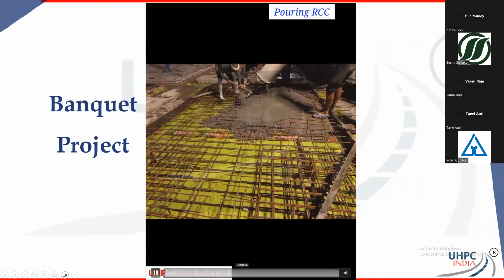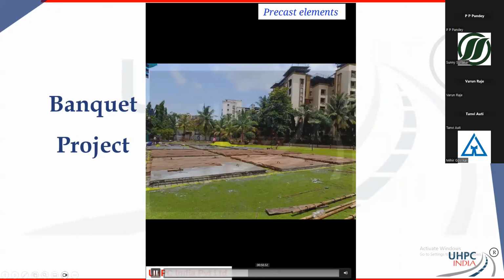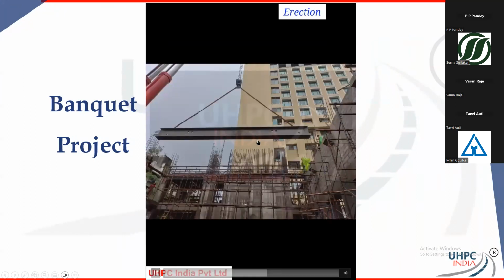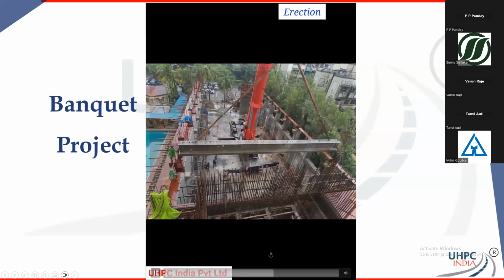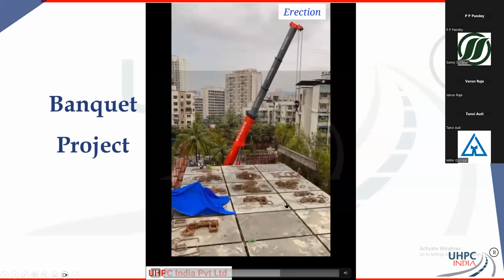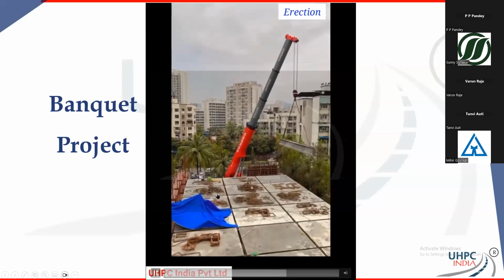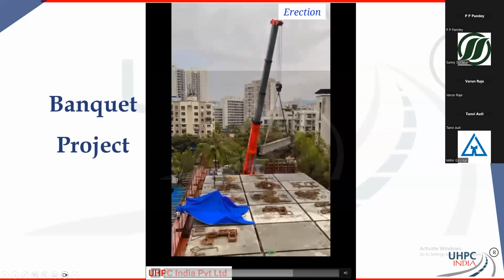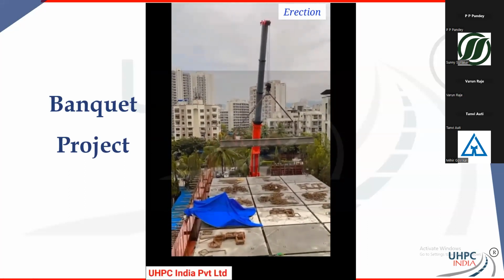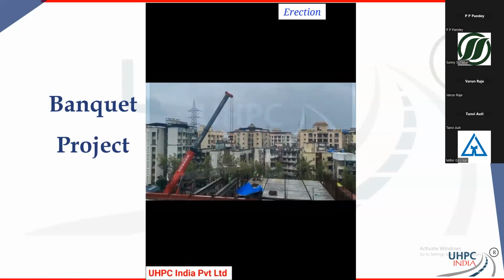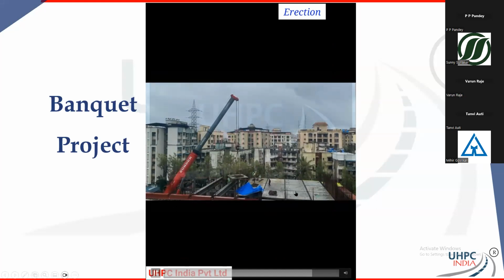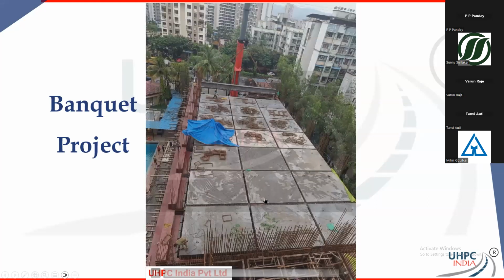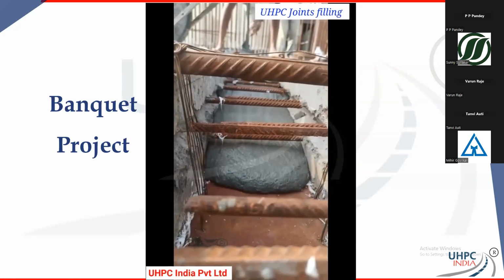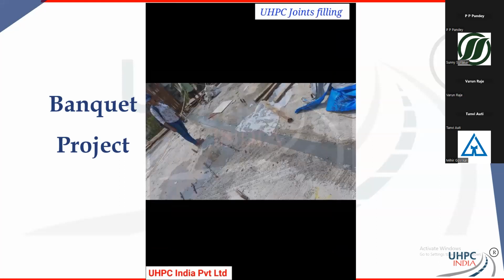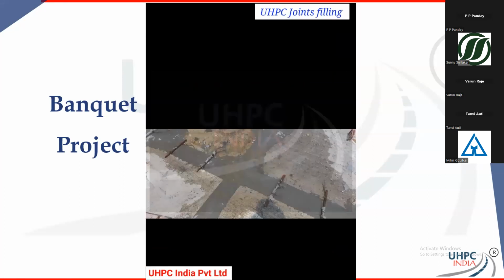UHPC was again done in transit mixers. You can see that everything was put together and pulled up, and the girders you can see now, the slabs you can see now, and all these joints that you see were then filled with UHPC so as to form a monolithic composite connection between slab to slab and to the girders. Now imagine, here you do not need any topping slab. Typically we put a topping screed of about 75 mm on precast, but here you get a fully composite connection and continuity of your deck, so you do not need any topping slab on precast.